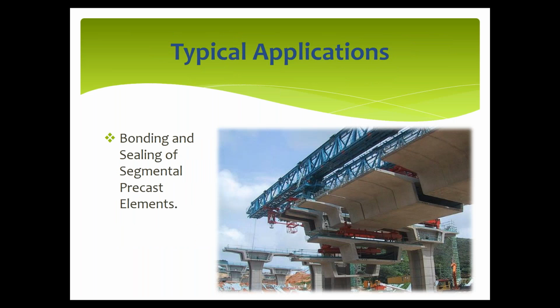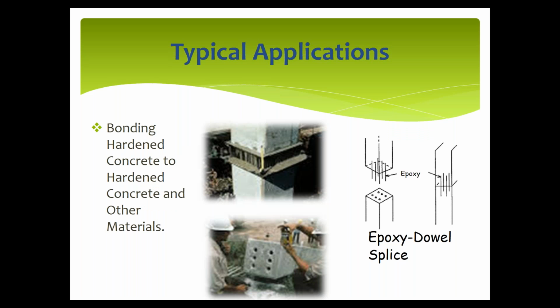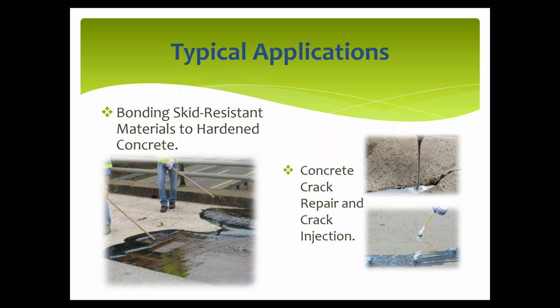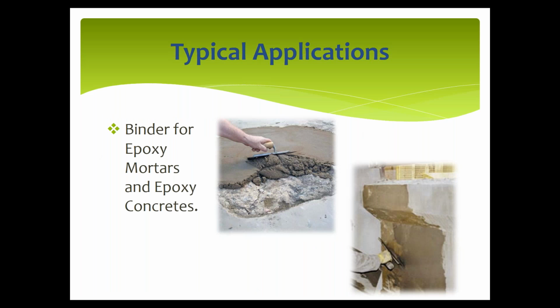A typical application for this product is the bonding and sealing of segmental precast elements, as shown in the picture. Another typical application is bonding hardened concrete to hardened concrete and other material. Also, bonding skid resistant material to hardened concrete, concrete crack repair, and crack injection. So you see, if your state has a high friction overlay product, it can be used. A binder for epoxy mortar and epoxy concrete, patching potholes and surface spalling of the girder member.